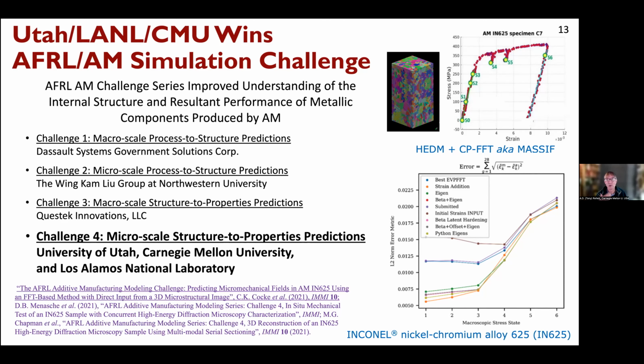It turned out there was more information in this initial data set than we had understood at the beginning. And when we included that initial information in the appropriate way, we were able to knock down these errors by a factor of about 2. And so we reckon that we were doing quite a good job in the elastic range, but less good as you get into the plastic range. So if you're not very impressed at how well we're matching things when metals go plastic, I don't blame you for thinking that, but I can assure you that this is the same story that we've been seeing from many, multiple sources, which is interesting.